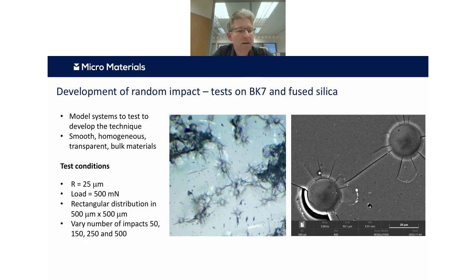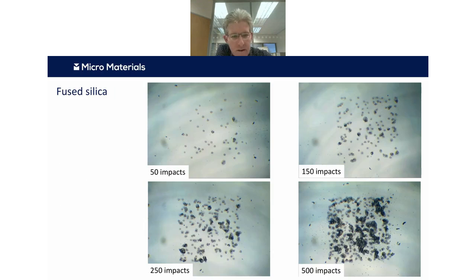So we studied this by changing the number of impacts between 50 and 500. If we look to start with, I don't know how well you can see that, but on the fused silica, we have 50 impacts randomly within this half a millimeter by half a millimeter area. There's not much overlap, but as we increase the number of impacts, there's more probability of these impacts being closer together, and this causes damage between them. You can see progressively as it builds up, and you're starting to get a transition to a more extreme mechanism by 500. So that's on fused silica.